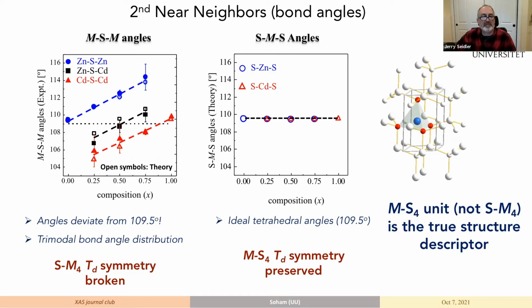Matt, you had a question about angles? Yeah, I think this is a related question. I didn't quite understand how the angles were calculated or determined. Is that from the XAFS data? This is from the XAFS data. These are just from the law of triangles, basic trigonometric calculations that you get from the nearest neighbor distance and the second nearest neighbor interatomic distances. So does that assume that the atoms all stay in the same plane? When we are estimating the distance between two atoms, let's say zinc to zinc, we are considering two different zinc, and the angle value that you see is an average of the two different zinc distances that you get.